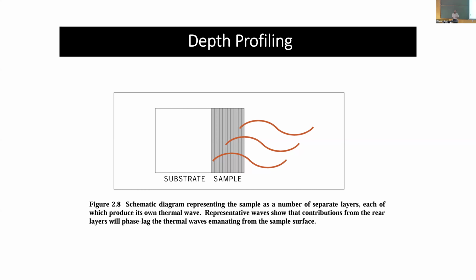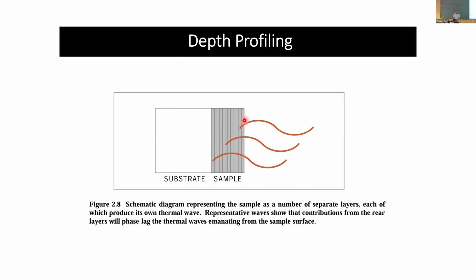So what you can do here is if you have heat diffusing, if you have absorption happening on the top of your sample, where the laser is passing in front of it, the heat diffusion from the top to the surrounding is extremely quick because it's happening right at the top.